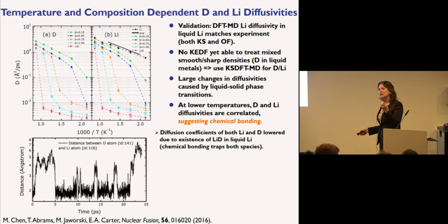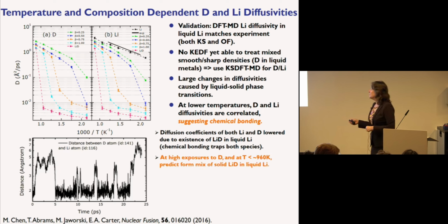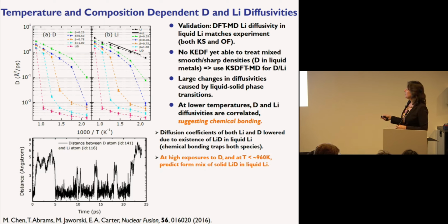And so what's happening is the deuterium is getting trapped in the liquid. And so essentially at these high exposures and at temperatures below roughly the melting point for lithium deuteride, we predict that you're going to form a mixture of solid lithium deuteride in liquid lithium.